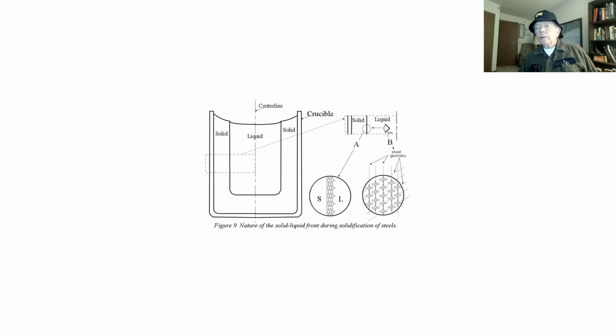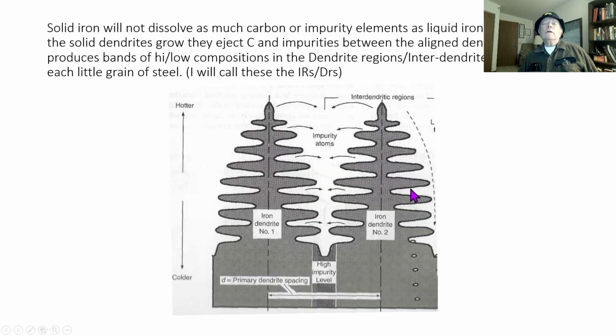I'll be calling those interdendritic and dendritic regions or bands or sheets, and they're lined up. And why? Well, that's because of the crystal structure of the solid that's being formed. Here are 2 dendrites growing up into the liquid. We have liquid up here. Solid iron will not dissolve as much carbon or impurity elements as liquid iron.